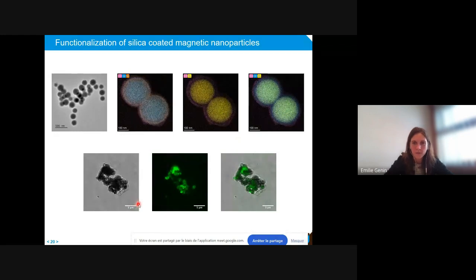We also did fluorescence microscopy experiments. Here you have the images with a classical microscope, here with the fluorescence analysis, and when you merge the two of them, we were able to prove that the fluorescent boronic acid is in fact grafted to the system.